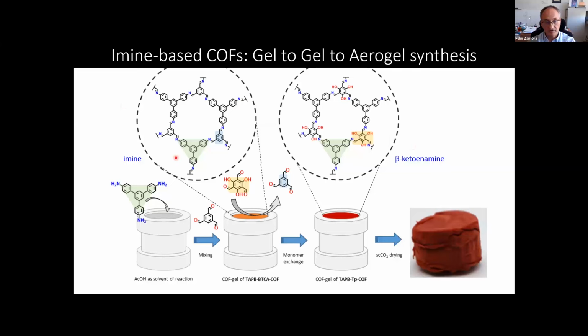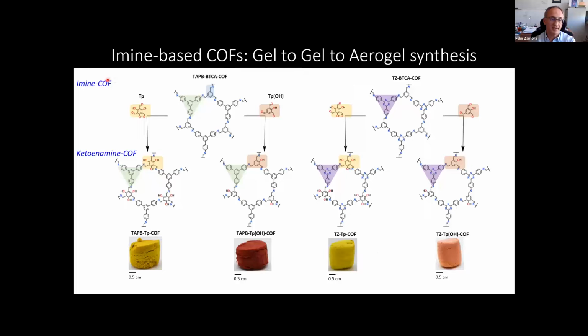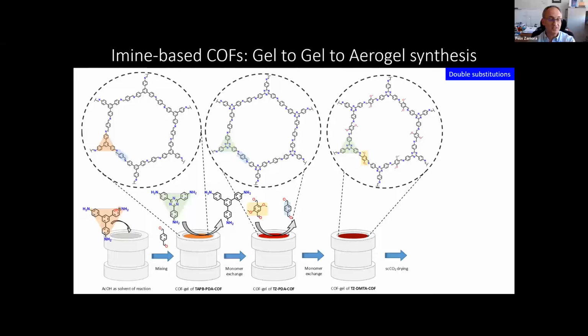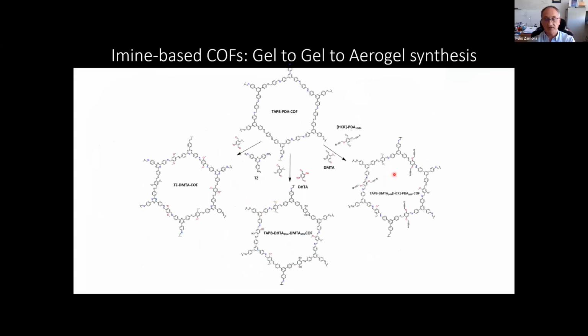So we run different reactions here to pass from imine to ketoenamine COFs by substitution of aldehydes. And here, as you can see, you can also run the reaction to first substitute not the aldehyde, but the amine. And secondly, you can eventually do a double substitution. Once you form the gel, you can substitute the amine, and you can substitute the aldehyde. And then you form a new structure. And you can run many, many different reactions.